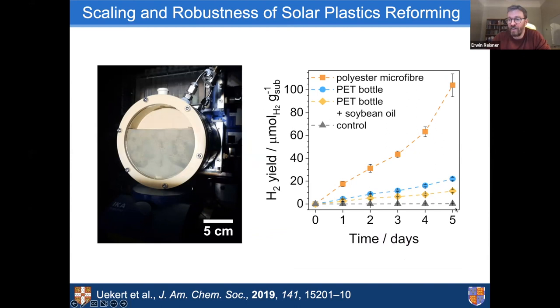Here's just one of these systems where we can see hydrogen yield over time. And what you can see is the polyester microfibers work really well. That may not be surprising because, again, they're already very small particles that can be broken down. So we have very easy access to our substrates. If we use a PET bottle, we see a bit of reduced activity. And if the PET is contaminated with some soybean oil, we also see activity.